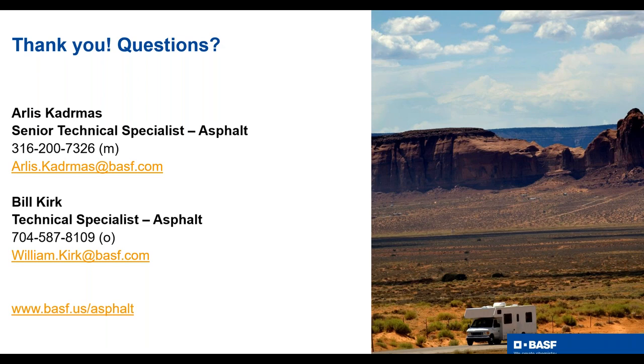You can make a little ball. That's why, using the DSR, you do a low temperature recovery procedure. You could have a glove on, make a little ball so that you don't get oils from your hand on it or whatever. And then you can put the ball on the little plates of the DSR and test it from there. So you don't have to heat up the residue if you're doing it properly with a low temperature recovery procedure. But that's one of the things that I'd want to make sure that folks do not do.